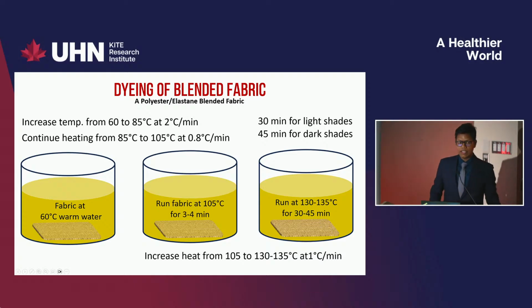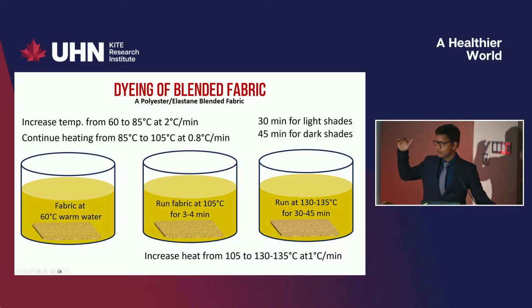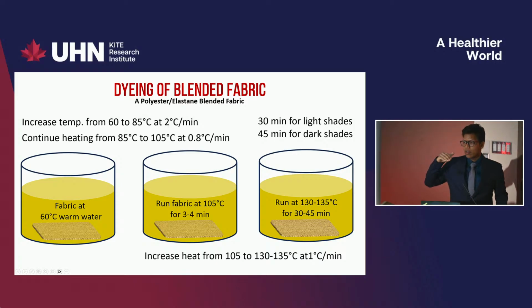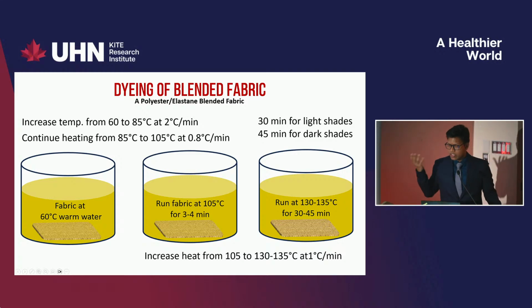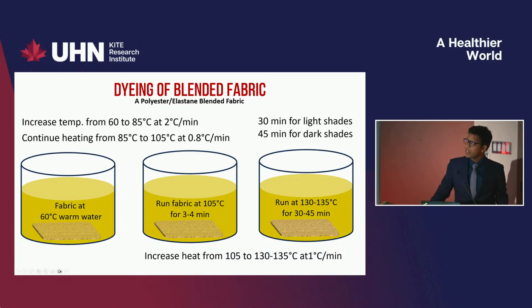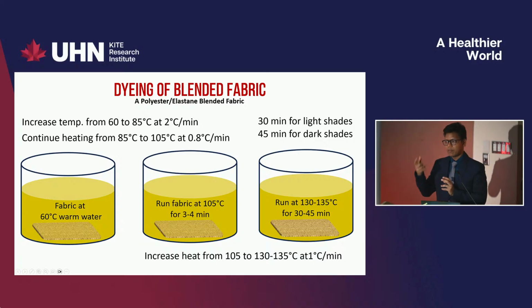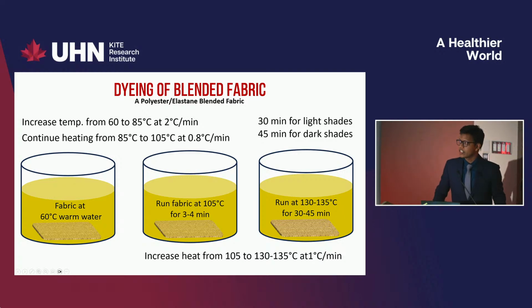So here I have two more notes about the shade. You'll see if we use the same color, we have different shades as well, a light shade, dark shade, and depending on the buyer requirement or the requirement of my material, I will run it lesser or higher time. So for instance, if I consider a very light shade fabric, yellow fabric, I'll run it maybe for 30 minutes. And if you want a very dark shade, I'll run it for 45 minutes or 50 minutes. And in the industry, we usually closely work with the lab department. Whenever we go for a bulk production, the lab department does a bench scale test. So they usually inform us what would be the running time in the bulk scale for the desired shade.